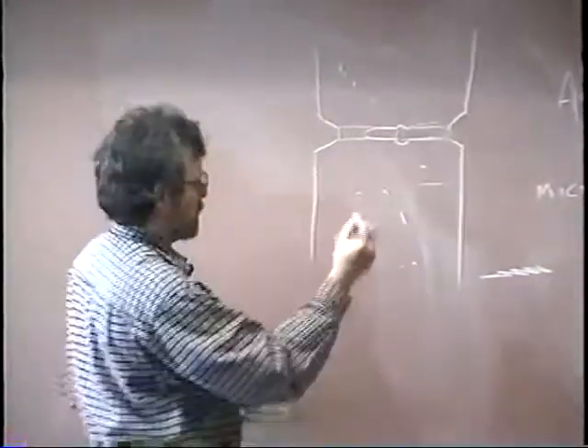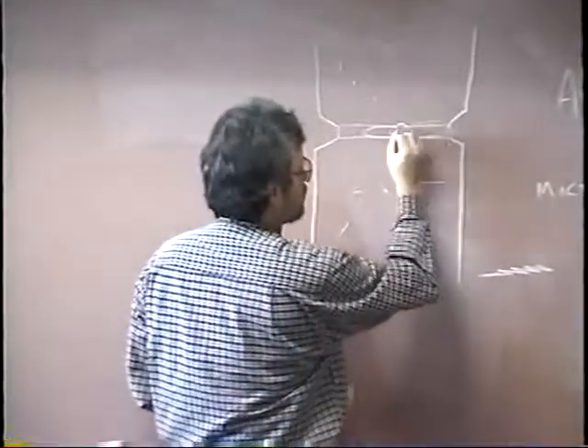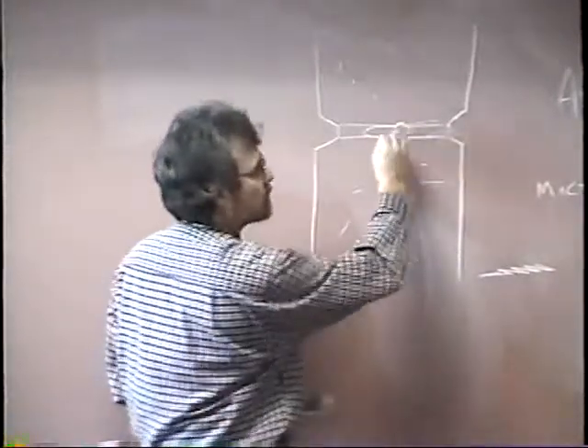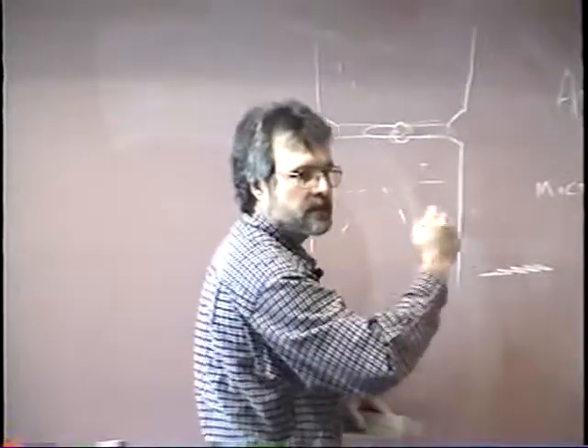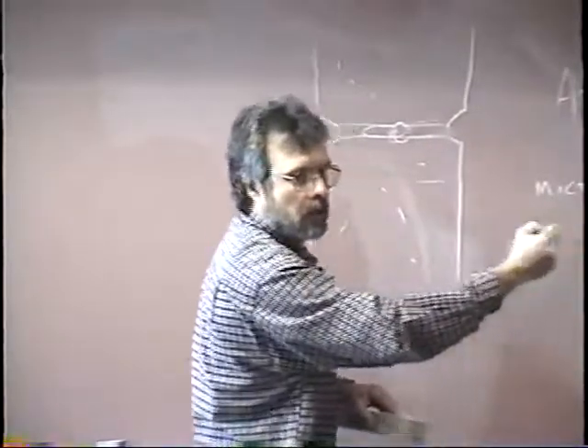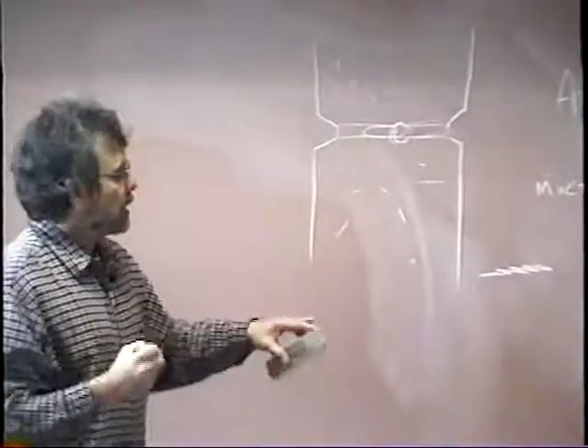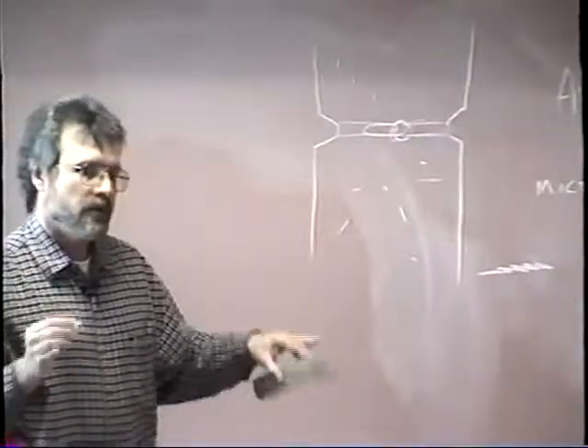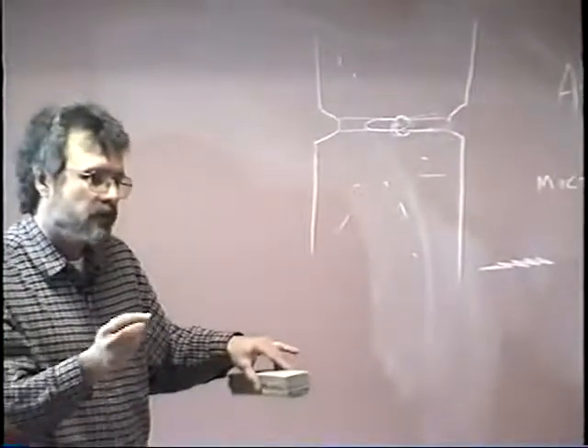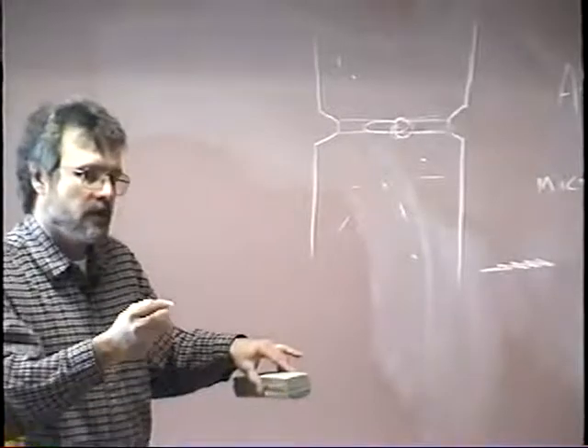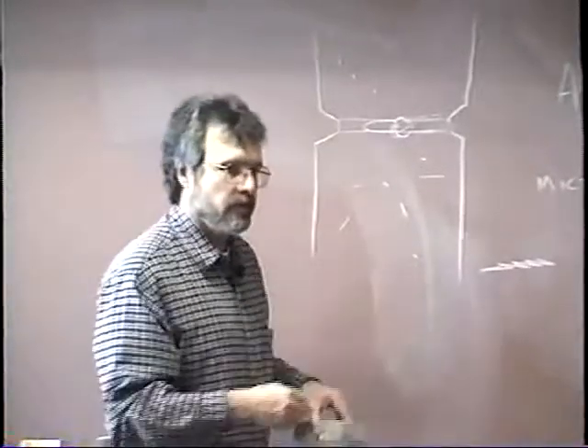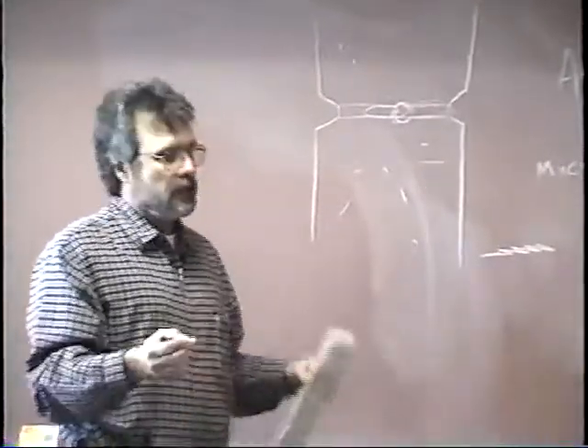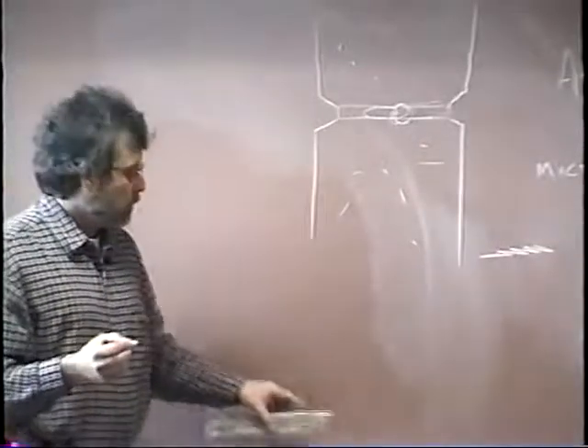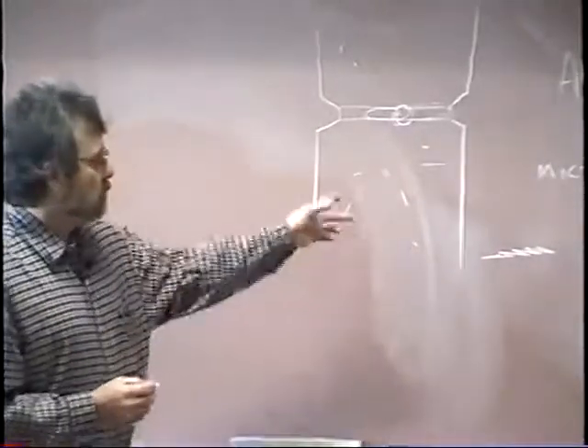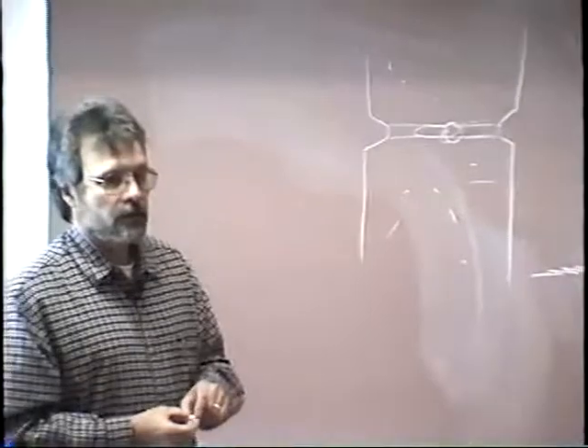I prefer, and I teach, just striking the arc, dropping back, tying into all those surfaces, and then using a consistent drag motion with it. That works just as well. If you're not getting enough penetration, then you can use this whipping technique to preheat and give you a little bit better penetration. But again, either technique will work for you, and I'd be happy to show you both as we go through this.